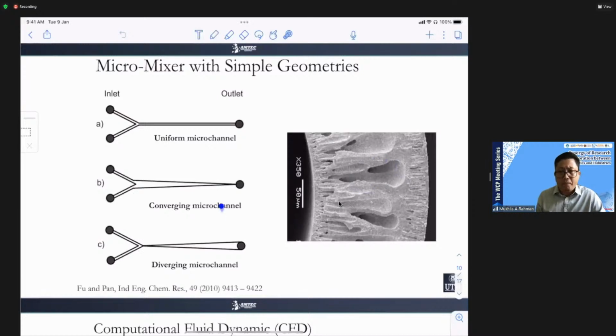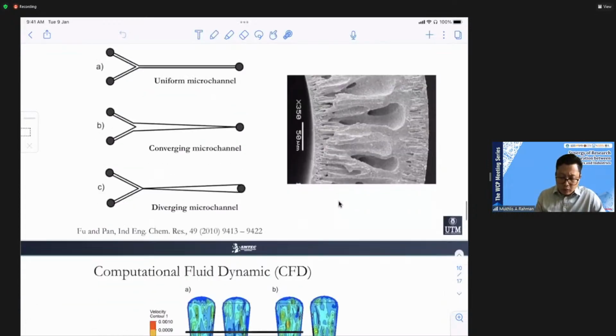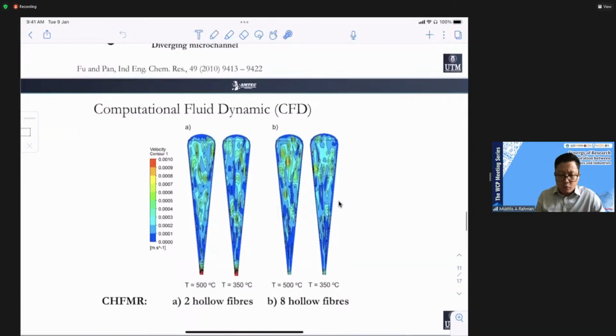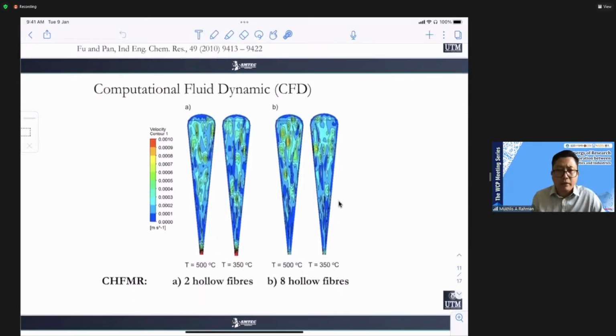We took this picture and compared it with these researchers, but these researchers also didn't prove how this diverging microchannel gives a good performance. But we took the opportunity and asked our colleague to do CFD, computational fluid dynamics. Instead of setting the environment to argon, at higher temperature, we set 500 and 350 degrees C. We want to see micro mixing, because in a catalytic reaction, you need a very good mixing process before you can convert the reactant into product.